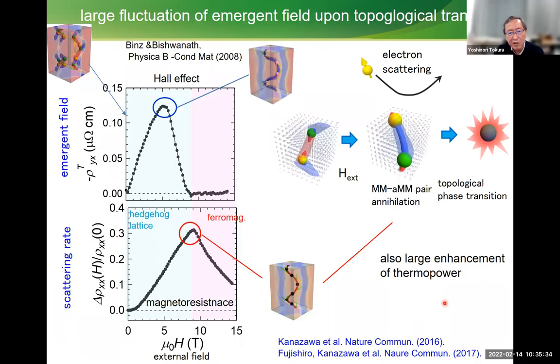Such a process can also be traced by the transport measurement. We measure the Hall effect. Hall effect is nothing but a measure of the emergent magnetic field. And then there is no topological Hall effect, but finally it goes to the longitudinal conical or ferromagnetic state, but in between the one skyrmion string is stretched out. So it reaches the maximum, and then goes down here. And this is a very large signal.